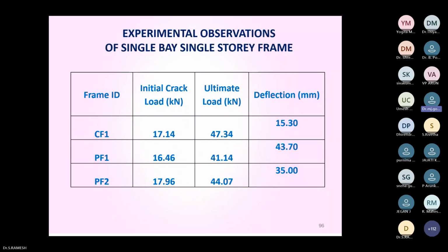This is the final result for the single bay single story. Experimental observations of the single bay single story frame. Control frame 1: initial crack occurred at 17.14 kilonewton, ultimate load 47.34 kilonewton, deflection 15.3 mm. PF1, that is specimen 1, the beam to beam connection joint: initial crack occurred at 16.46, ultimate load 41.14, deflection 43.70.